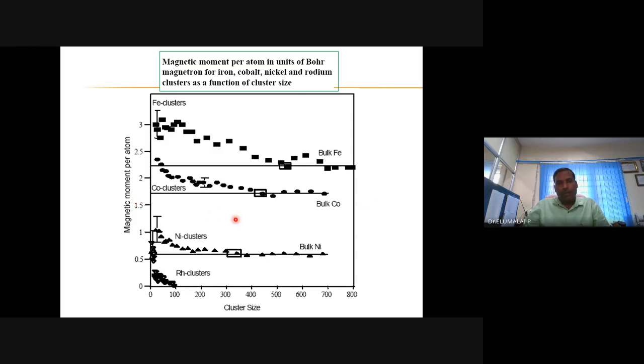Not only iron, but cobalt, nickel, even rhodium show an increase in the magnetic momentum per atom. But already the number of atoms is decreasing. We know that if the number of atoms decreases, the magnetic momentum will decrease. But per atom magnetic momentum will increase at the nanoscale. This is one distinction compared to bulk materials.